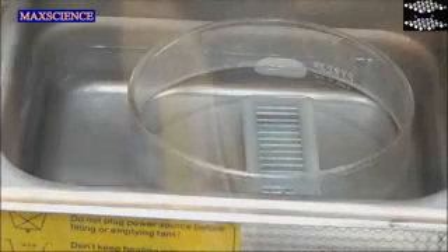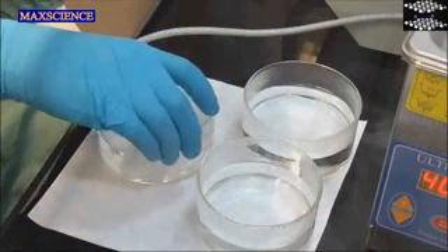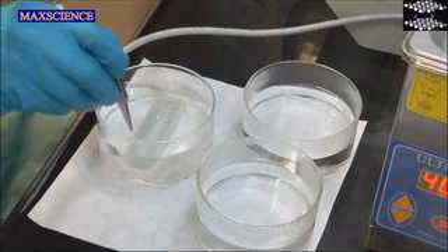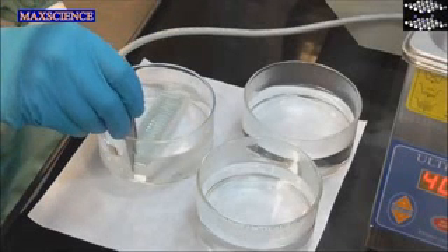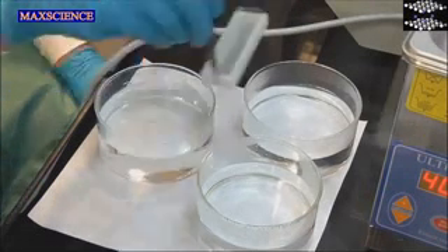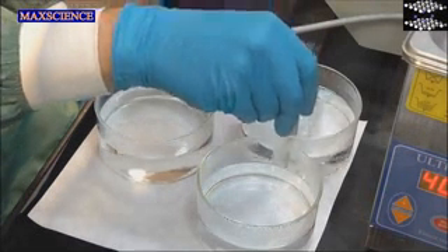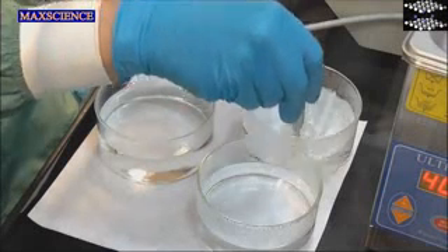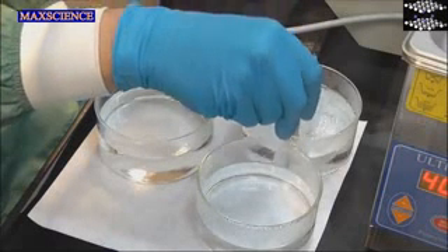After the 5-minute sonication, carefully remove the beaker. Be careful because the beaker might be hot. The substrates should now be dump rinsed in boiling deionized water. It is important to use boiling water to ensure no remaining Hellmanex solution is present on the substrates. Perform the dump rinse twice. After the dump rinse, make sure you change the deionized water.